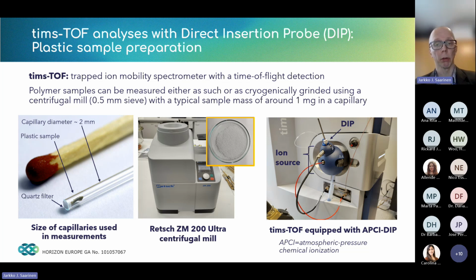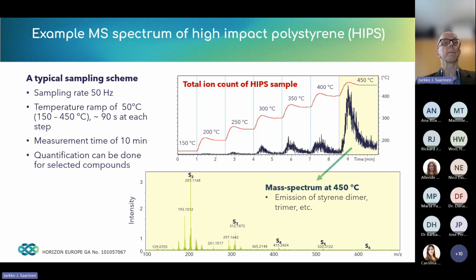The typical protocol that we use, which we have developed within the PRIMUS consortium. Here is an example mass spectrum of the high impact polystyrene. Roughly, it takes around 10 minutes to run the analytics. Our sampling rate is 50 hertz, so we can collect a very large amount of data from our measurements. We use a temperature ramp of 50 centigrade, and we run approximately 90 seconds at each step.